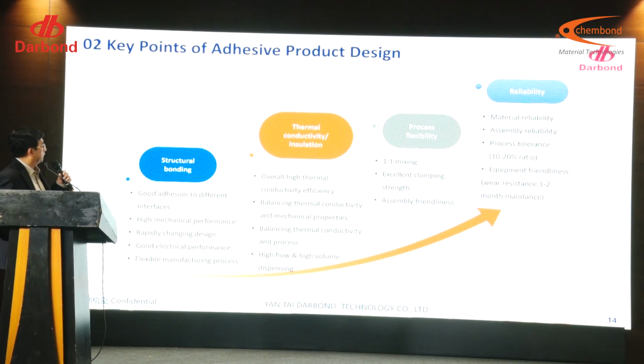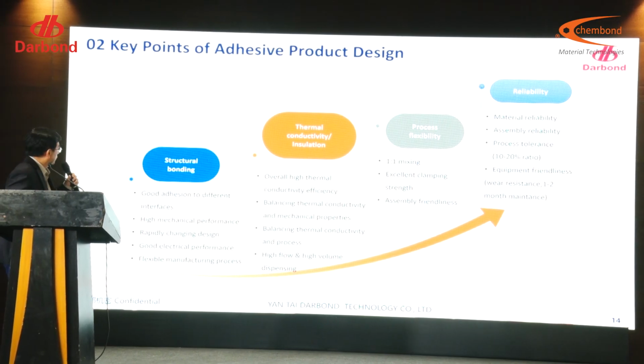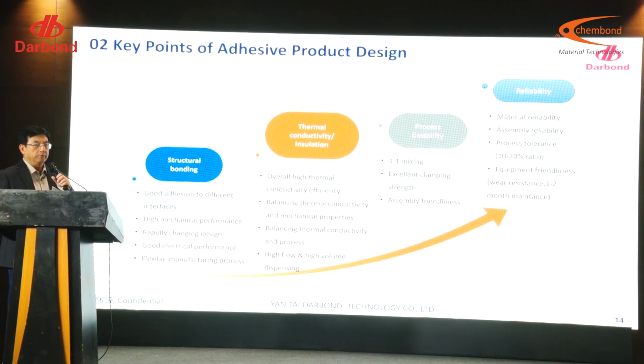We have to consider these 4 key aspects. So first is the structure bonding. For the structure bonding, for the EV lithium battery, you have different interfaces. So the adhesive has to have very good adhesion to different interfaces. Of course, this adhesive has to have high mechanical performance, the strength, especially impact strength. And the design is rapidly changing, and you need rapid upgrading of the material for the new generation of the EV lithium battery.